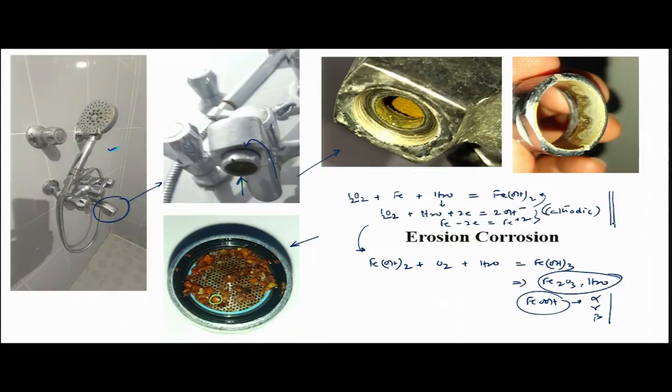At the same time, we have a scrubbing effect because of those sand particles and the turbulence created when the water is changing direction. And the turbulence will be high because this is a grid, and that grid is actually stopping the water flow, making it turbulent flow. And that grid is allowing those particles to be accumulated on top of it.